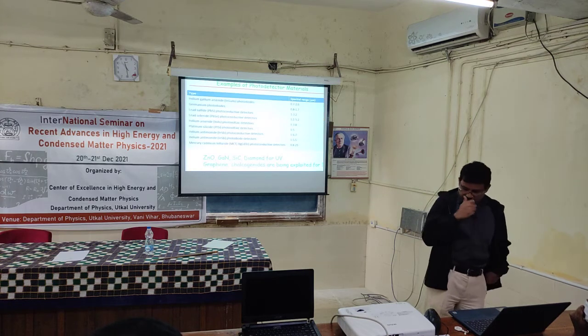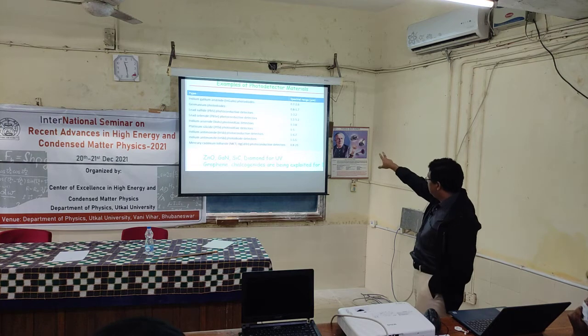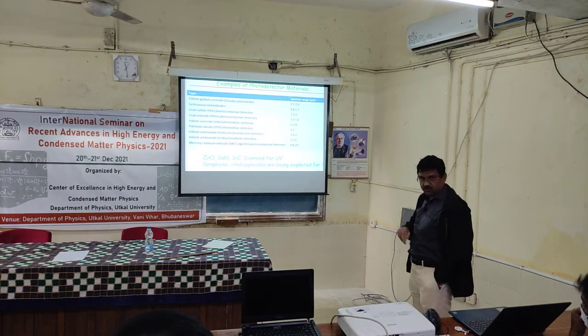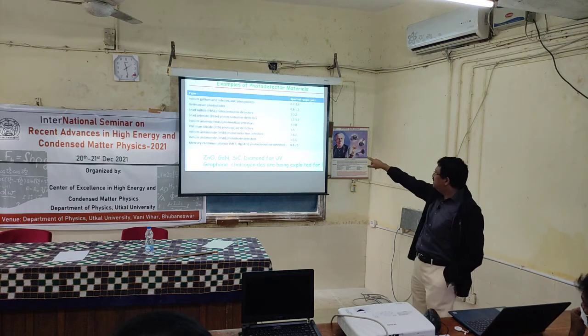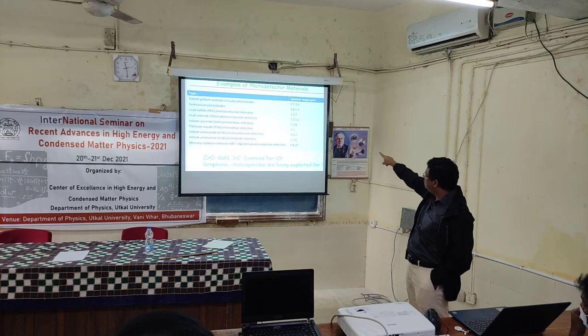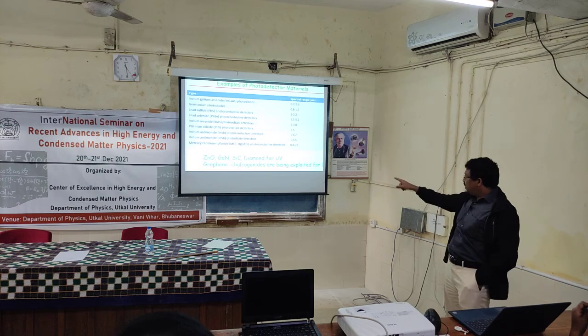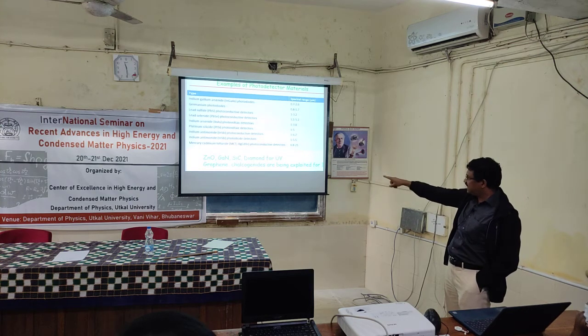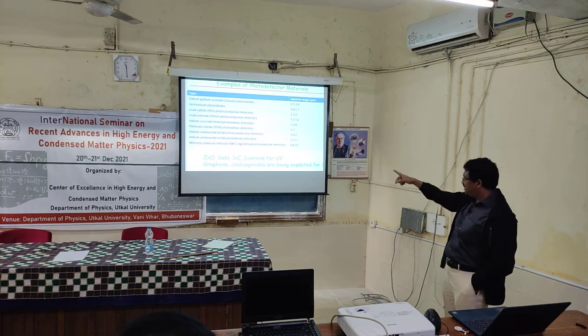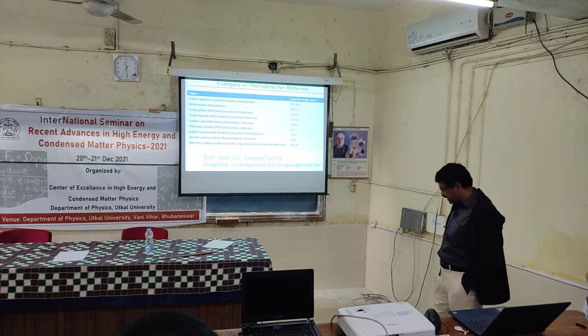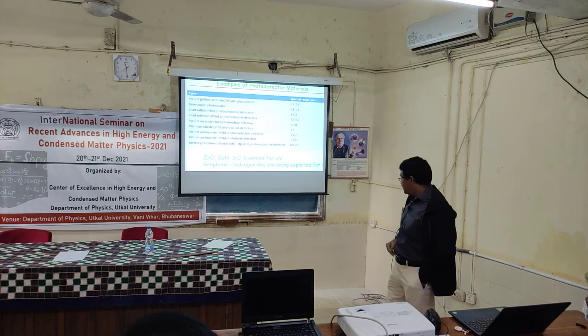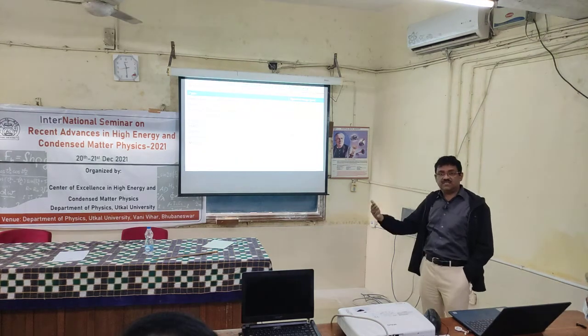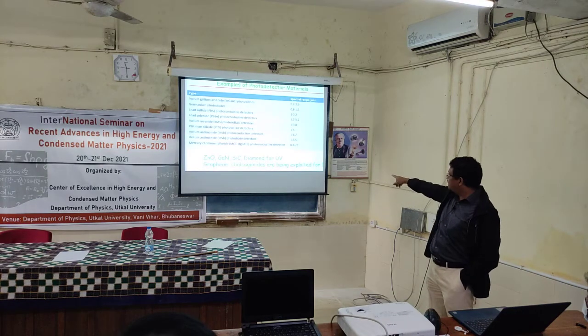Again, if you look at the literature, these are the materials and these are the spectral ranges. This is 0.7 micrometer to 2.7 micrometer. If I have to detect this range, then I can use indium gallium arsenide based photodiodes. If I have to use 1.1 micrometer to 3.2 micrometer, again this is for IR, then I can use lead sulfide. Similarly, these are the ranges and these are the materials we can use. For UV detection, we can use zinc oxide, gallium nitride, silicon carbide, diamond. If you go through the literature, you can find these materials being exploited for UV detection. And after the discovery of graphene, and of course the chalcogenide 2-dimensional systems, these are being explored vigorously for IR detection.